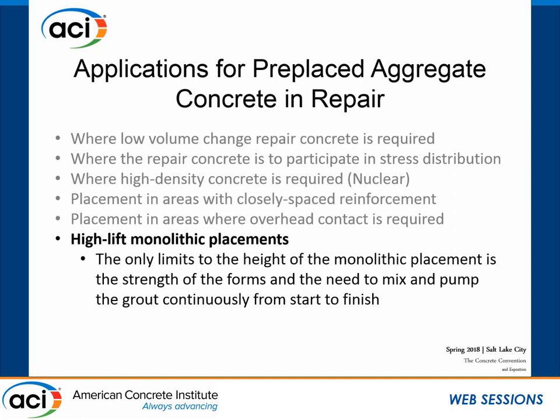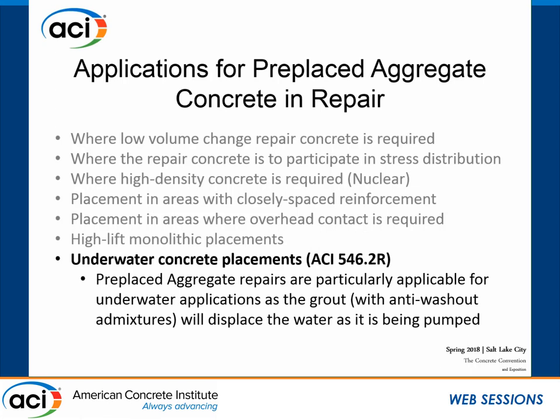The only limits for high-lift applications are the strength of the forms and the need to pump continuously — you can't stop or you'll have cold joints. And this is a very interesting one: pre-placed aggregate repairs work extremely well in underwater repairs. You might think the water would contaminate the grout, but with anti-washout admixtures that are available, you can pump this material in underwater, it'll displace the water, and create a very nice repair.